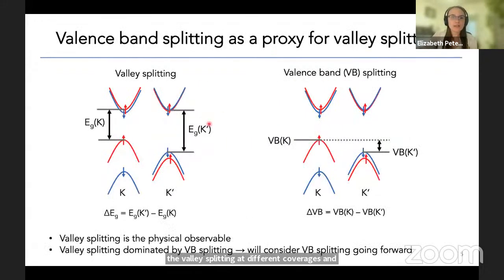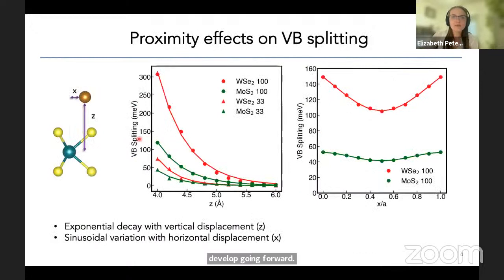And before I go on, I want to make sure I define these quantities I'm going to refer to clearly. So valley splitting is the difference between the dipole allowed band gap at K prime and at K. And this is the physical observable. This is what's observed in photoluminescence spectroscopy or reflectance spectroscopy. But what I'm going to talk about is valence band splitting, which is the difference between the topmost valence band at K and at K prime. And in my studies, these two quantities typically vary by no more than about 5%. And I'm going to use the valence band splitting because that's what's relevant to this model that I'm going to develop going forward. So we begin with proximity effects.